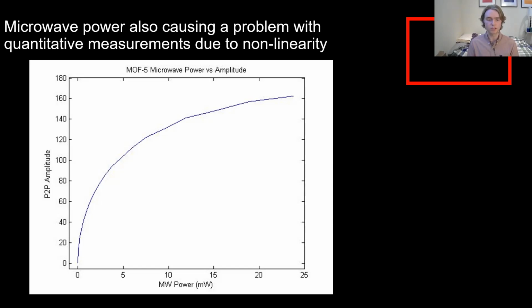But really what we want to be seeing is some type of linear region, probably right around near 0 microwave power. You might notice there are some places that look a little bit linear in the higher microwave power regions, but those are actually just due to the way the data was collected in this case. We would be really hoping to see a linear region closer to 0. Normally when you do quantitative analysis, you want to be measuring within that linear region where the relationship between the power and the amplitude is linear, because it can start to cause problems if you're working outside of that region with the quantitative analysis.